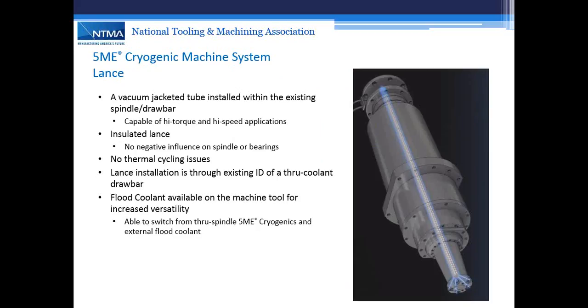The lance and rotary coupling. The rotary coupling sits at the back of the spindle, which is attached to a lance. And again, the lance is a very critical component. It is a vacuum jacketed system. It has an inner tube that carries the liquid nitrogen, and then a tube around that with the vacuum extraction like we talked about earlier.